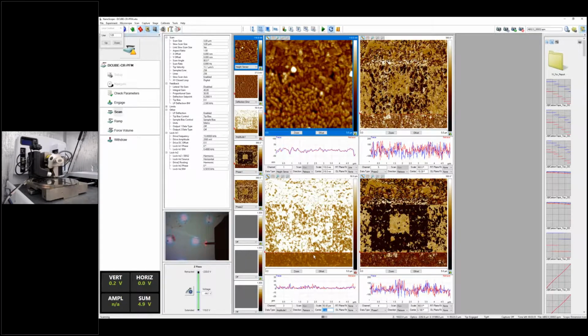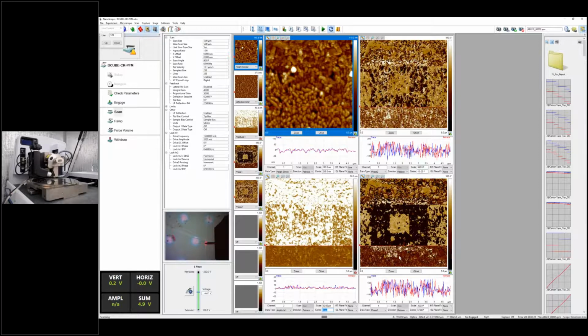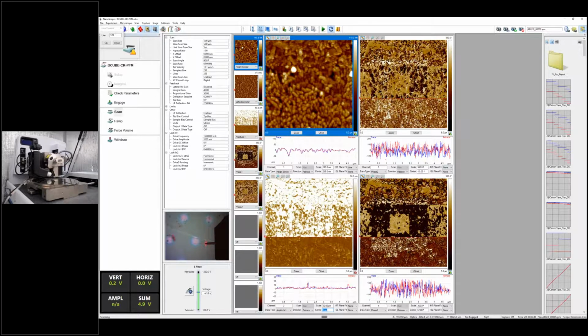And from there, you can see that at each grain, the response can be different at the same off-resonance frequency. We also see from the phase channel that you have a very distinguishable orientation distribution, plus and minus 90 degrees. Although it's noisy now, part of the reason is that I opened the hood in order for you to see the video footage from my webcam. So usually we suggest doing this kind of measurement with the acoustic hood closed to screen out the environmental noise. Another part of the reason for the noise is that the amplitude is now quite small.